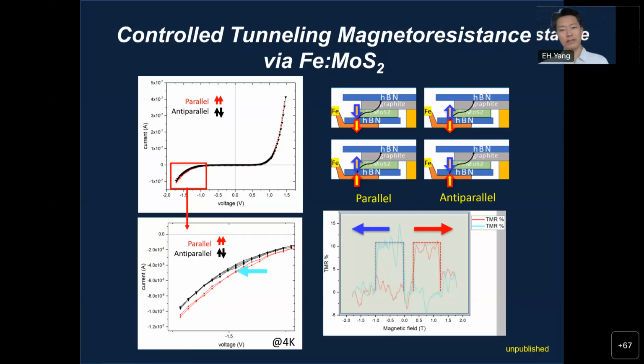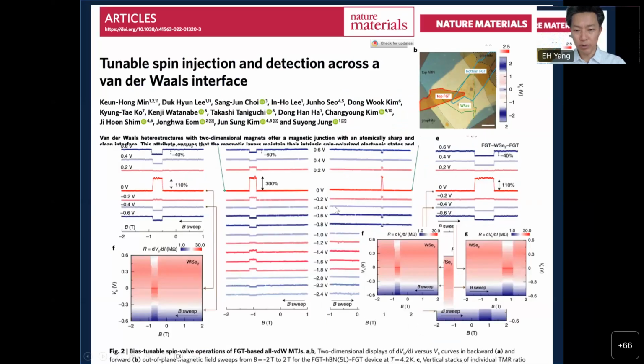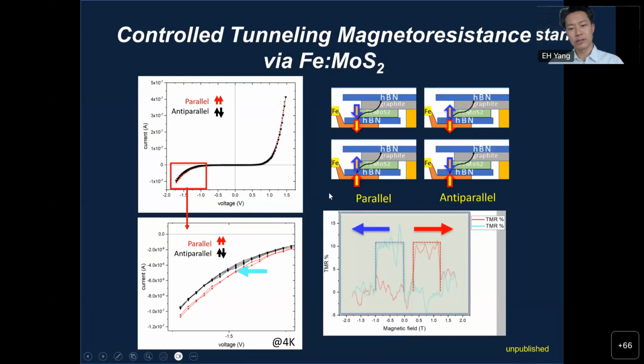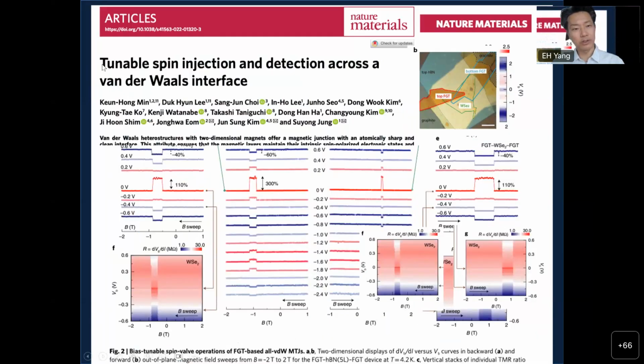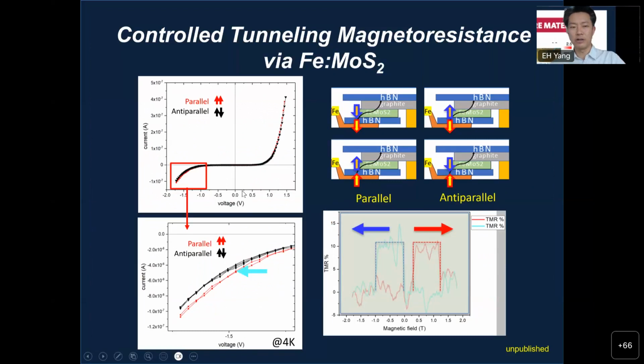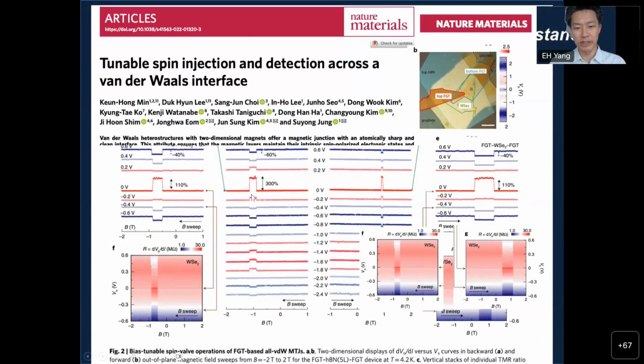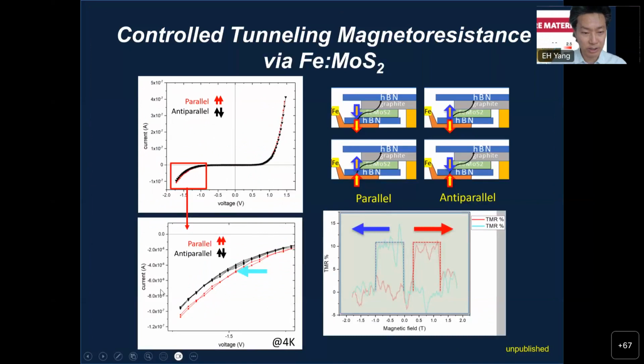All right, so that's what we have, and this is still sort of an initial result. We are getting much better data now, but I cannot show that. But we had issues with this noise. We thought that maybe this is because of the instrument, or maybe because this iron is rough. But then we looked at this Nature Materials paper on a tunable spin injector. Basically, it's the same tunneling magnetic resistance, just with fancy wording. But then we realized that they use a microamp level. In our case, as you can see, it was a nanoamp level. We have other technical issues, which is why we had to go low, but this is not a fundamental issue. We can make it large.